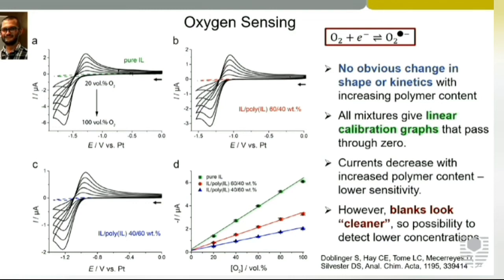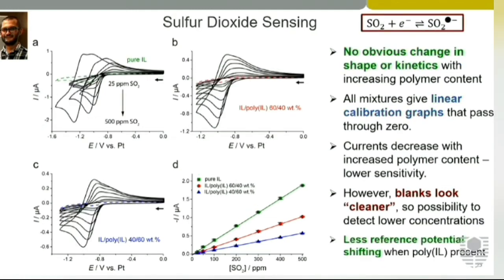But there's no change in the peak shape, so we're not seeing resistance and things like we did with some of the other polymers. And in fact, I'll show you more on the next slide, but the blank signal is actually cleaner the more polyionic liquid we add. And we think that's because it's much easier to purify solid materials, so polyionic liquids can be purified easier than liquid ionic liquids. And this has actually meant that we can get lower limits of detection for oxygen, which is good, but the real important thing is that we can get lower limits of detection for toxic gases, where we need to be able to detect really small concentrations.